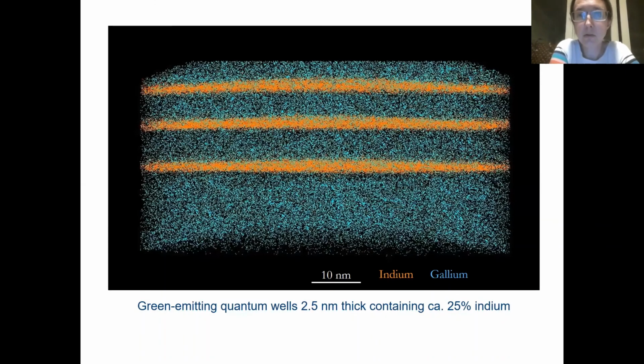Okay, and this is the sort of data we then get out of the atom probe. What I'm looking at here is the data that we've collected, reconstructed to make what is actually a 3-dimensional render, although I'm showing you a 2-dimensional image of it. Every tiny turquoise dot in this image is a gallium atom. I'm only showing you about a quarter of the gallium atoms because otherwise there would be an awful lot of blue everywhere and it'd be hard to see what's going on.